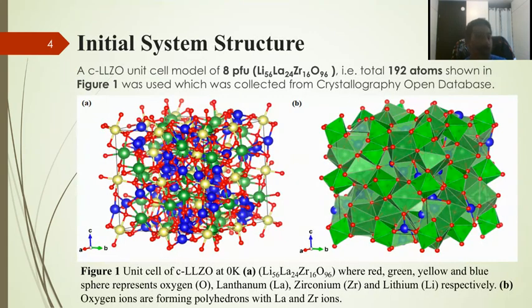You can see this is the initial system structure for our model. We have used 8 formula units, so 8 combined cells as a unit cell, which has 192 atoms, where we will mainly be focusing on the blue spheres, which are the lithium atoms in this cell. Let me tell you one thing. We have 56 lithium atoms here, but for these 56 lithium atoms we have 120 available sites in this unit cell, which come from the 24d tetrahedral site and also the 96h octahedral site. Next,